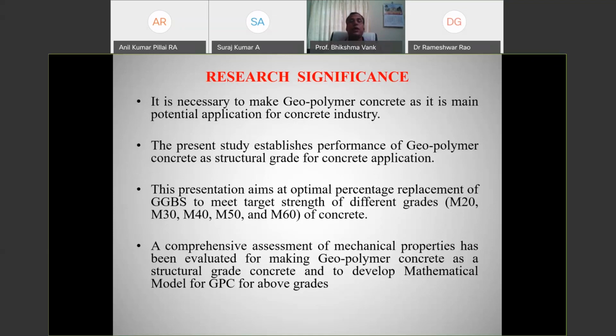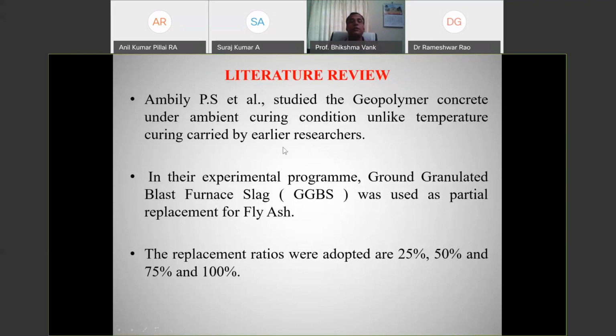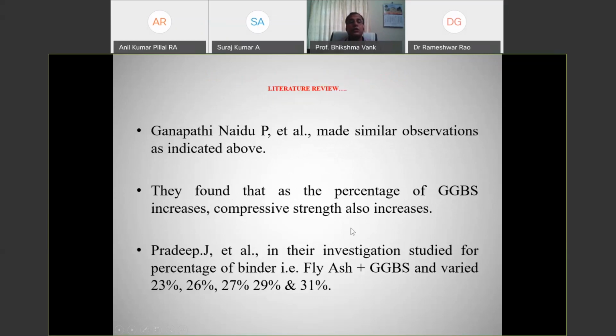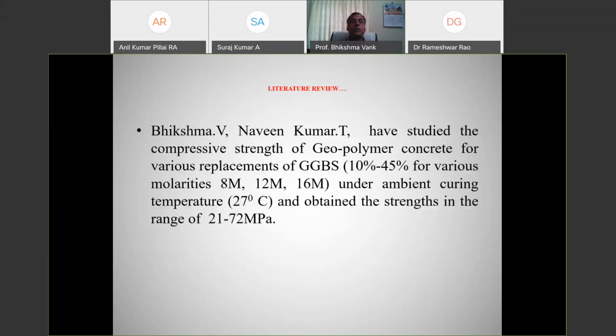The investigation was carried out at Osmania University on geopolymer concrete. These are some of the literature reviews done by several researchers. I don't want to go deep into the literature review here, but I'll try to explain the procedure of obtaining the compressive strength, the several trial mixes of geopolymer concrete with addition of GGBS, and replacement levels. Replacement ratios adopted were 25%, 50%, 75%, 100%. I can tell you all the details. Many people have done work on this using GGBS, but nobody established the grades.